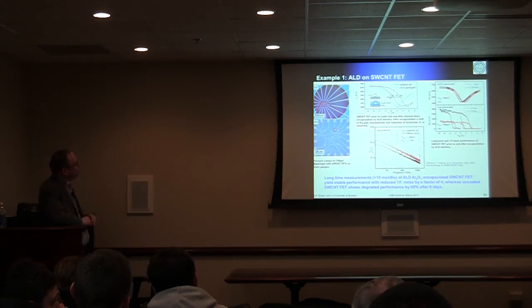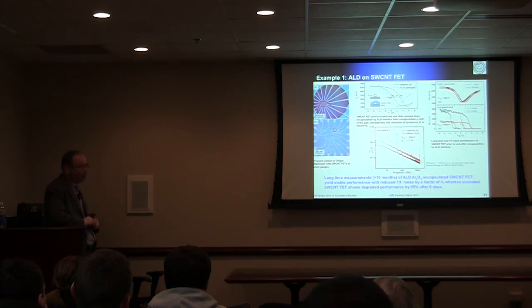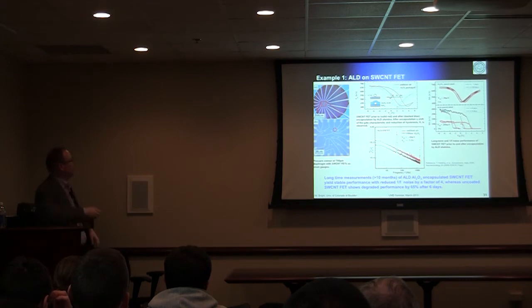So one thing we've been looking at for ALD for carbon nanotube devices is the carbon nanotube transistor. Again, this work is a collaboration with the ETH group. What we've done here is very simple. In fact, they make the carbon nanotube transistor, and the contacts in this transistor degrade pretty quickly over time. So if you look at these